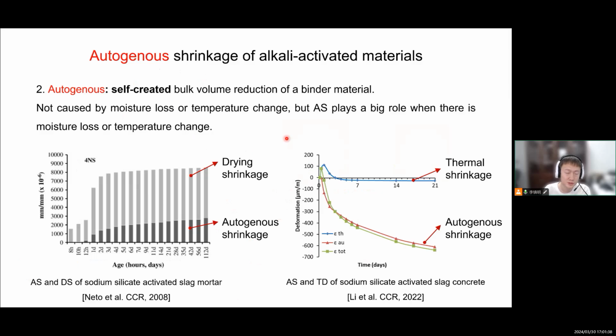Another reason why we should study this topic lies in autogenous, which means a self-created shrinkage. It is not caused by moisture loss or temperature change, but autogenous shrinkage still plays a big role when there is moisture loss or temperature change, for example, in drying shrinkage or thermal shrinkage. So autogenous shrinkage accounts for a big part. That's the reason why we need to clarify this phenomenon first before we can clearly understand drying shrinkage and thermal